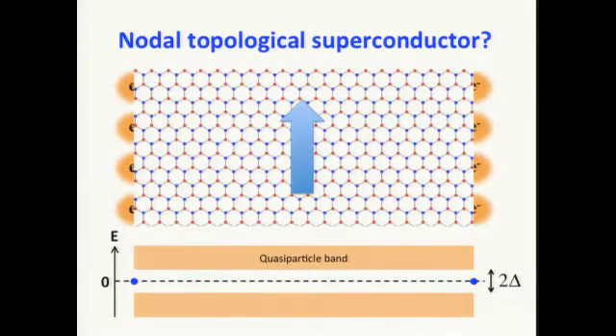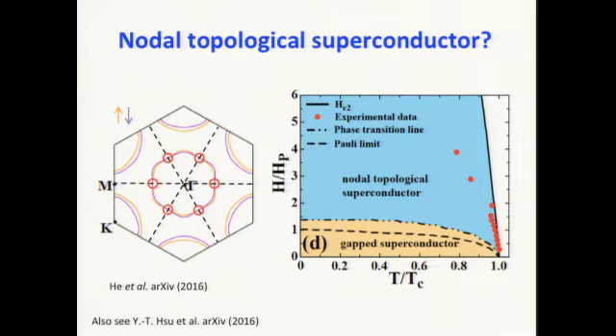You have these six points where the gap is closed, right? Yeah. And that is where you suspect the Majorana will come from. Yeah, this is the bulk band structure. When they close, the material will turn into a topological superconductor, so we expect some edge modes will show up. But there are 6 points at which it closes. So if there's some kind of coupling, then that will potentially ruin the Majorana fermions. Is that right, or will you see 6 degenerate?